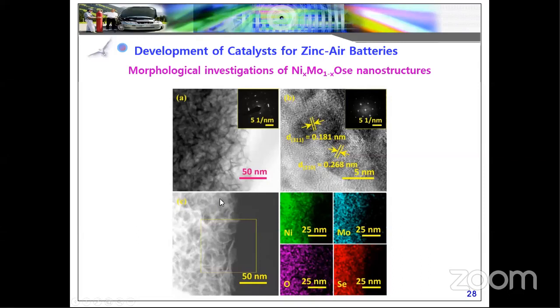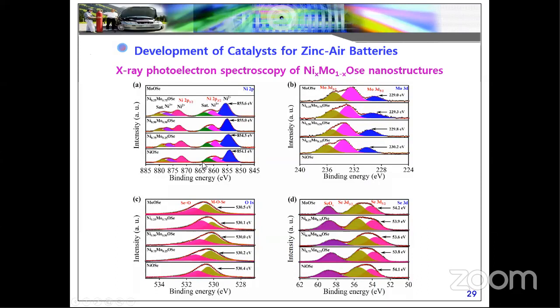You can see the metallic brighter area, and the nickel, molybdenum, oxygen, and selenium are homogeneously distributed over the ultrathin nanosheets. This is further confirmed by XPS, through the elemental compositions and the binding energy. The binding energy of our materials fully matches with the reference deposition, fully matching with the nickel oxygenates. But in our studies, we want to tune the morphology. That's why we are doping molybdenum with different ratios, 0.25, 0.5, 0.75.